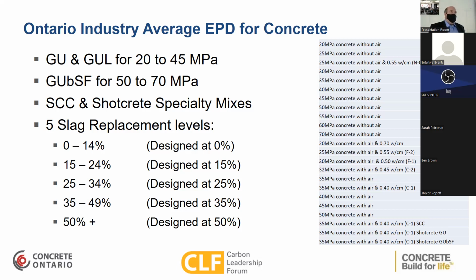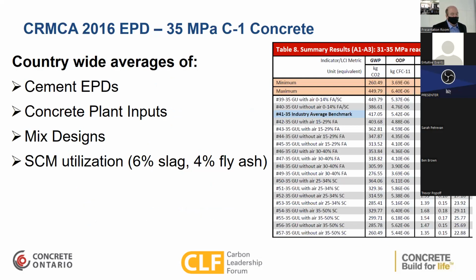In Ontario, we primarily use slag as our supplementary cementing material. So we've identified 5 different levels of slag replacement to give the contractor, the designer, and the owner a handle on what the different levels of performance are that you can see when you're looking at trying to measure carbon intensity. So for example, I'm pulling some data here, 35 MPa from 2016, averaged across the industry.